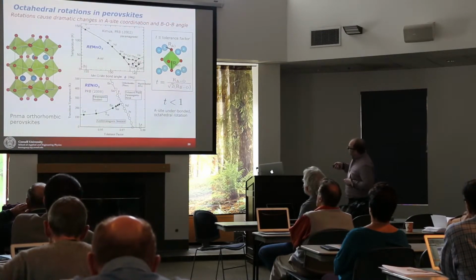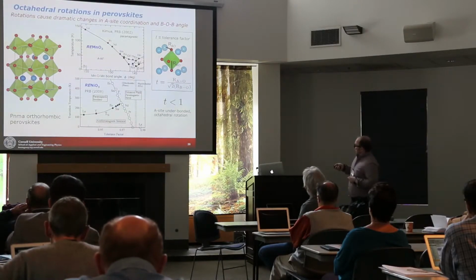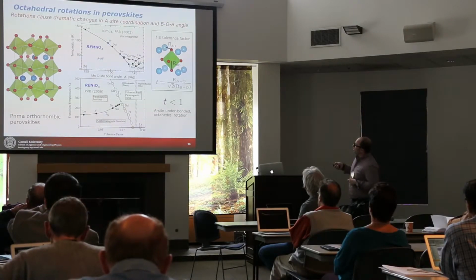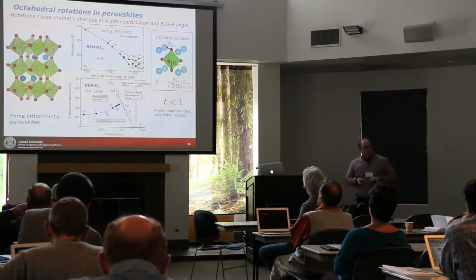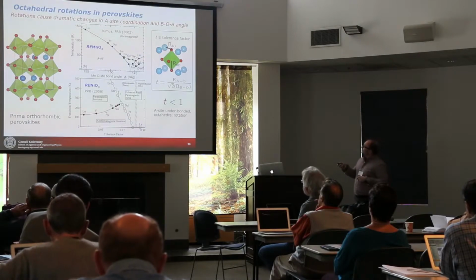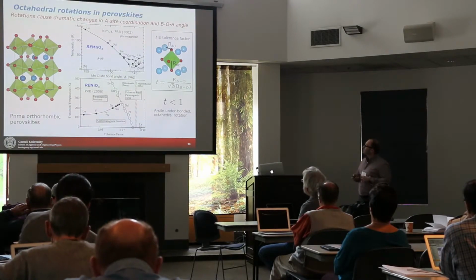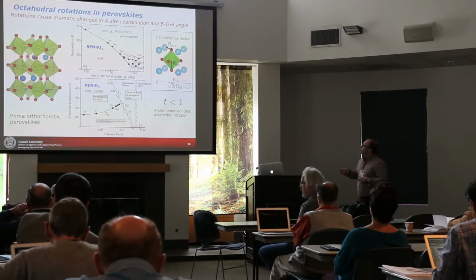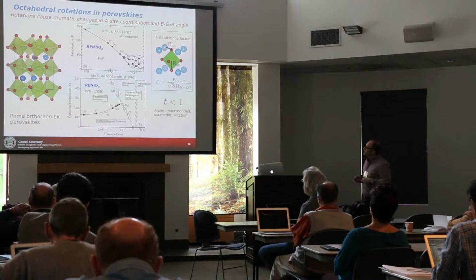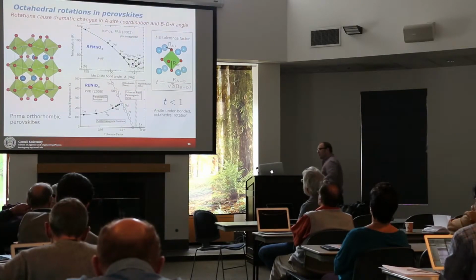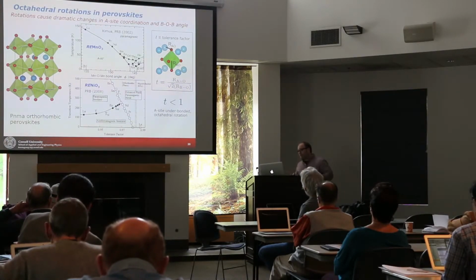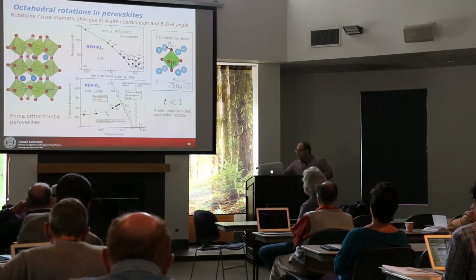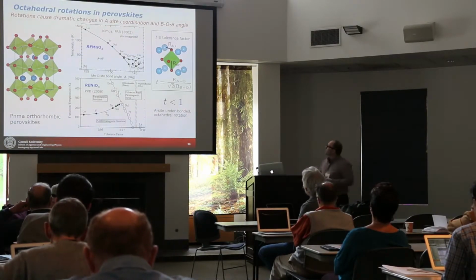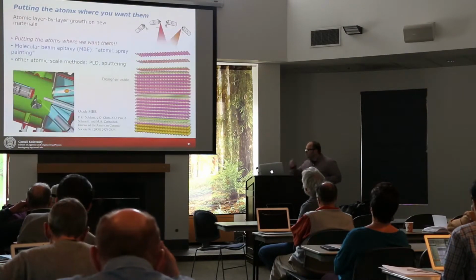As the A site gets smaller, the tolerance factor gets smaller, and the system distorts more and more. These very subtle rotations completely control the correlated ground states of these materials. You can completely tune between different magnetic states in this rare earth nickelates, completely tuned from a metallic phase all the way to an insulating phase just by changing the rotation angle, the rotation patterns, et cetera. These small distortions are key to understanding and controlling the properties of these materials.